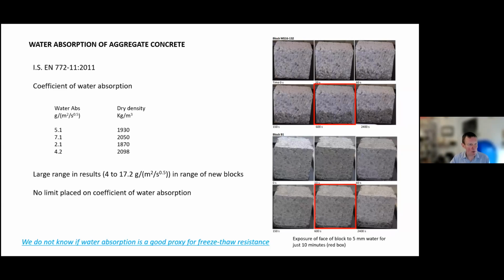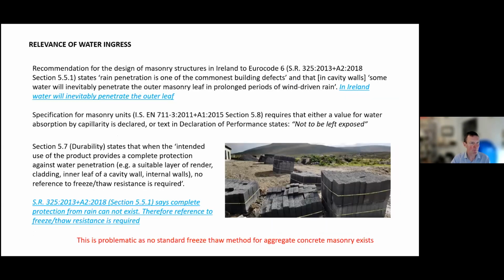We've done a bit of experimentation, and this is with Paul Quigley, and Michael Robinson is also involved in this. There's a very large range of results in new blocks. But unfortunately, there's no limit placed on the coefficient of water absorption in the standards. And we don't know if water absorption is really a good proxy for freeze thaw resistance, yet it is something that most manufacturers would quote.